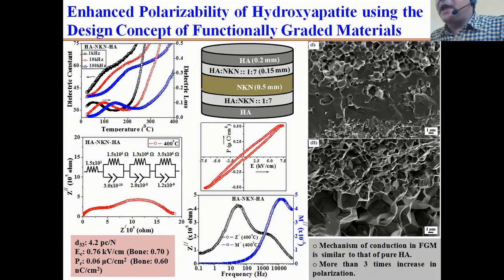But at the same time, if you see, the coefficients of thermal expansion are very different for sodium potassium niobate and for hydroxyapatite. So with any of the processing techniques, even with spark plasma sintering, we have seen delamination between these two layers occur, right? Or the strength was not good. So just to address this issue, we have tried a number of ways, and you can see in between the hydroxyapatite and NKN, there is one more layer that has been introduced.